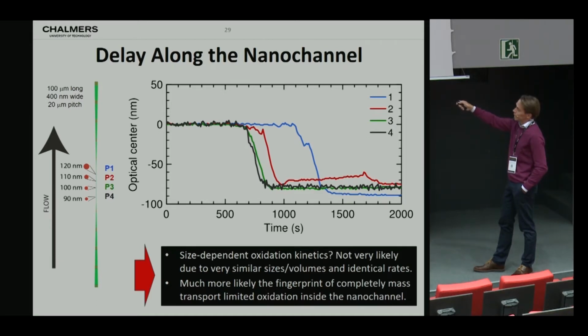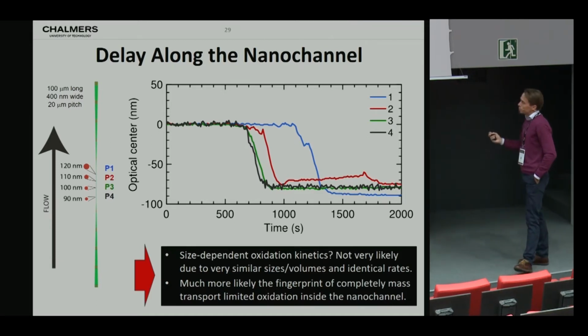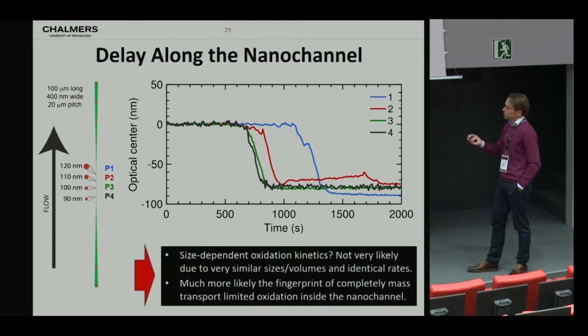There is just a delay for when it starts, which I believe, and I find this very exciting, is the fingerprint of a completely mass-transport limited oxidation process inside the channel, which means that we supply, due to the small dimensions of the structure, so little oxygen that it is all consumed by the first particle, the black one, which is the one upstream where the reactants reach first.